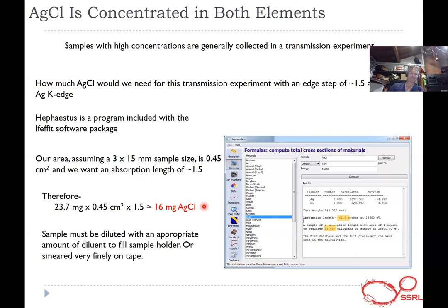And so for some of our bigger sample holders, 16 milligrams of silver chloride may not fill it, so you might have to dilute it with boron nitride or some kind of low X-ray interacting, X-ray opaque filler material. People use boron nitride, sugar, and in some cases silica. Or you can smear it very finely on tape and spread it out, which is kind of my preferred method. That way, if you underestimate, sometimes you can just double up your tape layers.